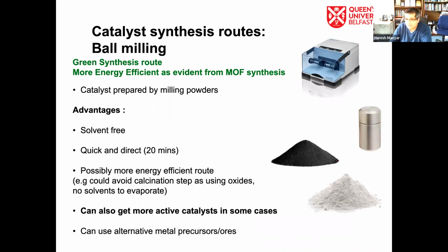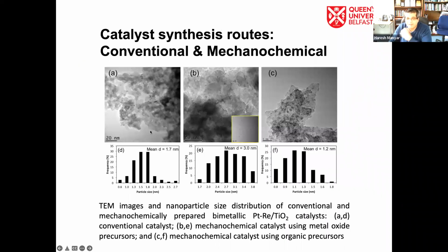Another advantage is that we can make this catalyst mechanochemically. So mechanochemically, we can grind it. And as you can see here, we can easily achieve the narrow particle size distribution with mean average particle size of 1.2 nanometers of platinum, which is even better than what we were getting through the incipient wetness technique or the wet impregnation techniques for making this kind of materials. So mechanochemical materials here are very good.